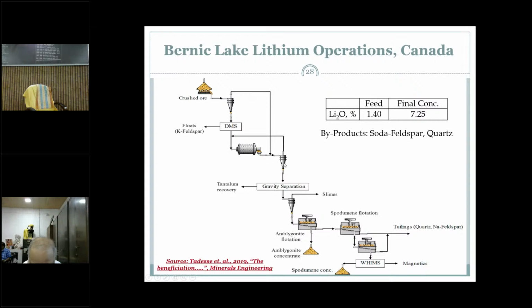The ball mill is in closed circuit with the cyclone. The underflow will be subjected to a gravity separator, and the gravity concentrate is having the tantalum, and the gravity tailing is subjected to again two stages, one stage of rougher, two stages of cleaner flotation cells to get the spodumene concentrate, and amblygonite is also there along with spodumene. The final concentrate is assaying about 7.25 percent.